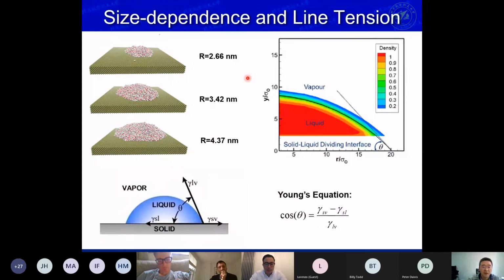First, we look at the size dependence and the line tension effect. We can use MD to simulate different sizes of droplets, for instance, like here. And then we can measure the density contours for each droplet. And the liquid vapor interface is composed of the points that have half the liquid density, and then we use a circular fit to get a circle through the points, and then extrapolate to the solid liquid dividing interface or the substrate. Here we can measure the contact angle.